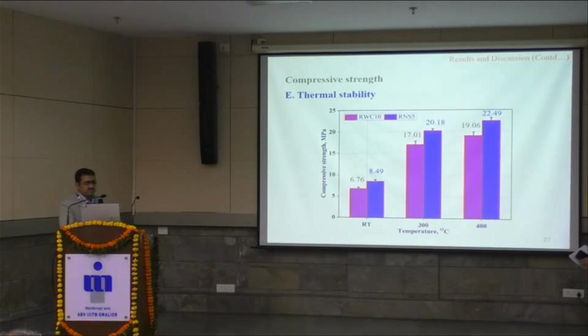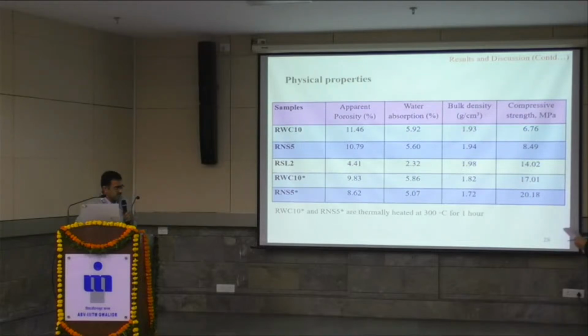It was the test for thermal stability. When the product after 28 days was treated at 300 degrees centigrade and 400 degrees centigrade, an increase in compressive strength was observed. These were the physical properties. Apparent porosity is in fact less than 17, so it can be used for applications with a good strength of more than 20